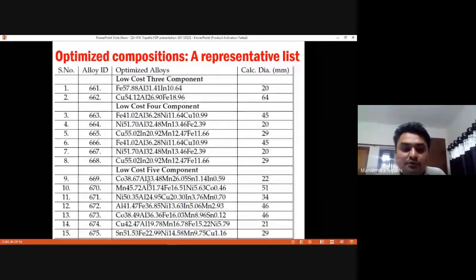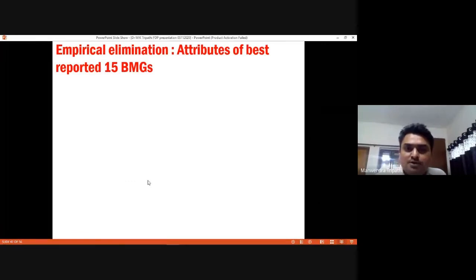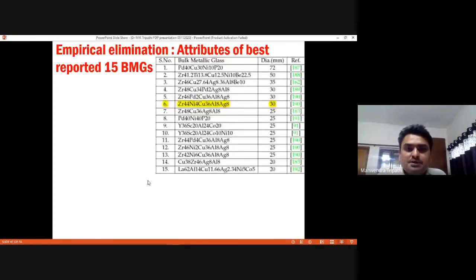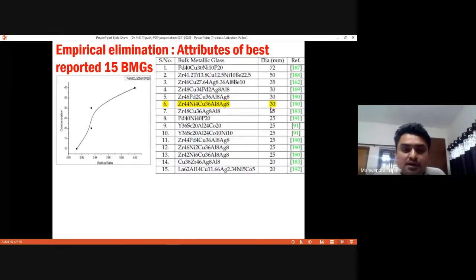We have again used a filter, so that compositions which are not proper should be removed before going to the experimental phase. These are the globally best known compositions, and the best known is 72 mm, palladium based, then again zirconium based, right? These compositions are 72 mm to 20 mm, and we are treating these as reference compositions, because we are comparing our compositions with respect to these, which were giving metallic glass.